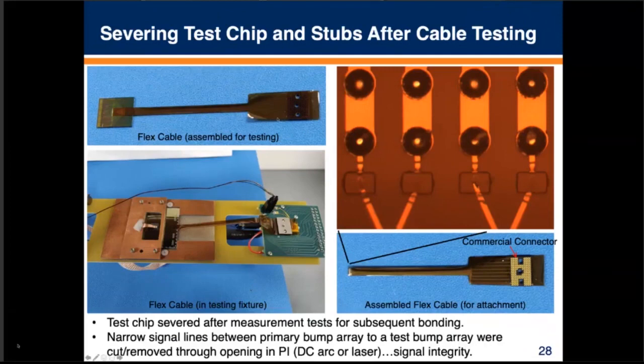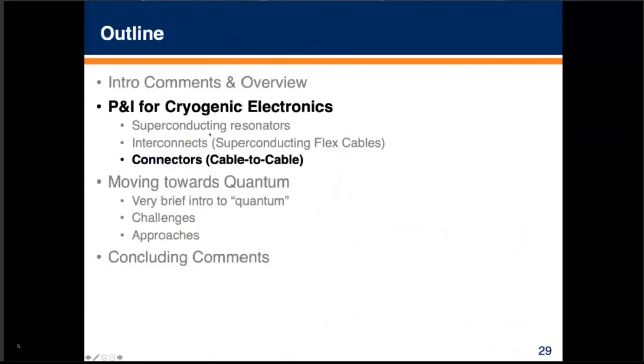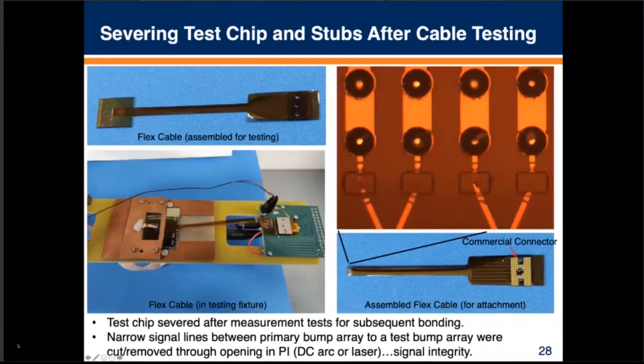To test these structures when you've got indium bumps, that's a challenge. The approach we've taken is we connect it to a small test chip, and we can test it that way, at least from a DC perspective, and then just cut that chip off, leaving behind a small bump array that you could use as your functional bump array. In our case, we have these little openings in the polyimide, and we can either laser remove those or use a small DC arc to essentially vaporize the traces in that space. Then you're not left with a big stub hanging off of here that might potentially cause problems with the microwave performance of the structure. And you can see the tape sitting here in its measurement fixture as well.